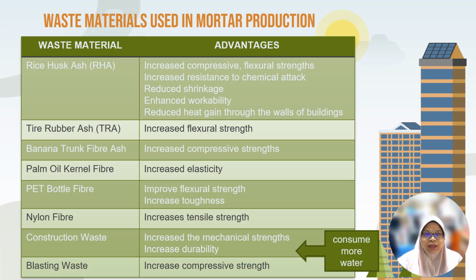The table shows a summary of the differences in the results of the study. It can be concluded that waste materials, whether in the form of ash, fiber, or crushed materials, can increase compressive strength, flexural strength, elasticity, and workability. In addition to the advantages mentioned, it was found that mortar made with recycled aggregate consumed more water to reach the same level of workability as conventional mortar because of the greater porosity of the recycled aggregate.